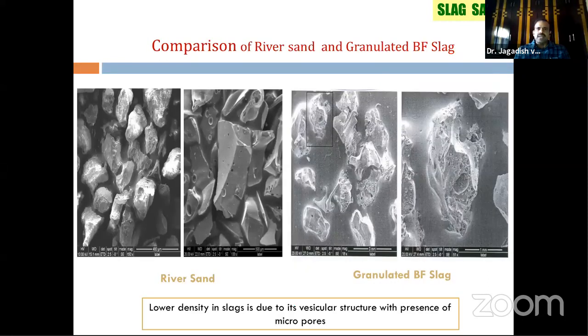So they did microscopic studies comparing river sand and granulated blast furnace slag. Because if you have to use it as a river sand, it should meet the properties of IS 383. When they looked into it, it has a lower density, like 1000 to 1100. It contains a vesicular structure, and this structure contains micropores. That means you have more pores, so water absorption will be more when compared with the river sand, and obviously low density, and also specific gravity is less. So when you have to use it, you have to match with the requirements of the IS 383, and it should match with the natural river sand properties.